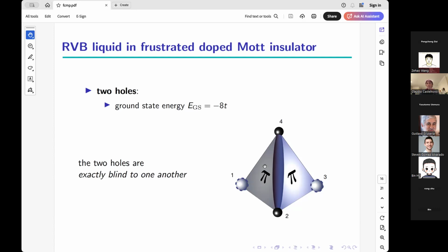So the hole 1 is able to resonate with 2, 4. 3 is able to resonate with 2, 4. But beautifully, they're able to do it at the same time. Because if you swap 1 and 2, for example, then 3 is no longer resonating with 2 and 4, but resonates with 1 and 4. So it always continues to resonate with a triangular face. It just changes as the holes move and hop around. And the holes are obviously hardcore objects. You cannot have two holes on the same site.